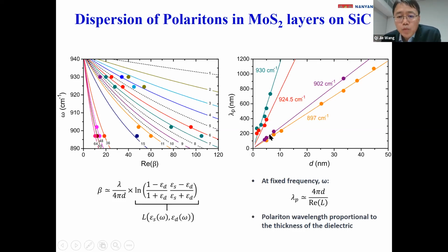Okay. However, when we reach the thickness of this 2D material from 3 layer to below to 1 layer or bilayer, we indeed see some mismatch between the experimental result and the theoretical predictions. So one reason would be, the permittivity of the 2D material at the monolayer and bilayer would be quite different to that of the bulk material. And however, in the literature, unfortunately, we couldn't find the accurate and detailed study about the permittivity of the 2D material, especially in the mid-infrared region.